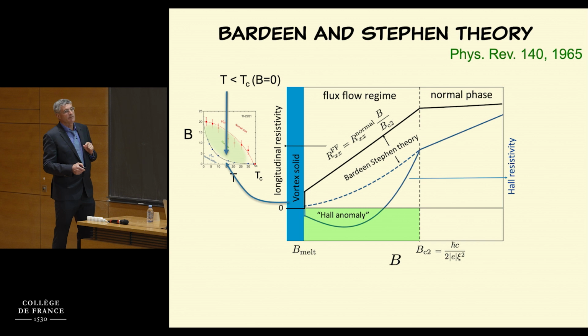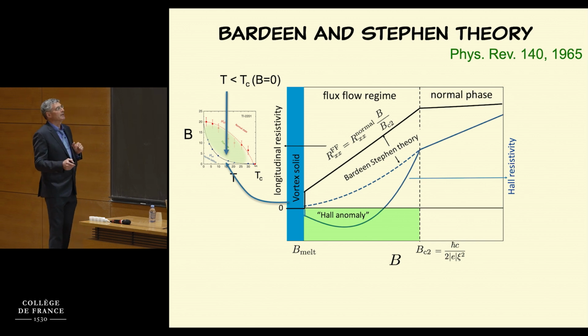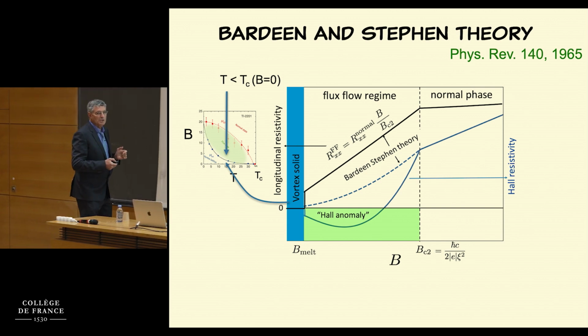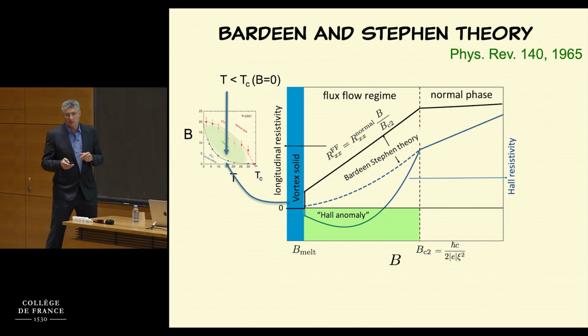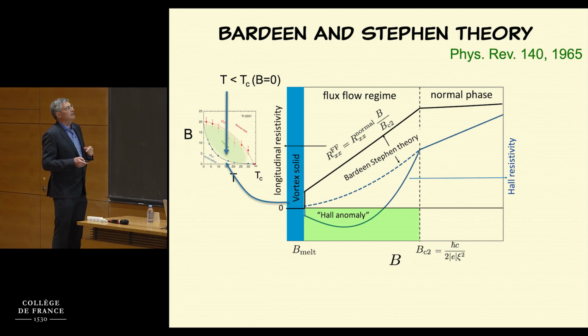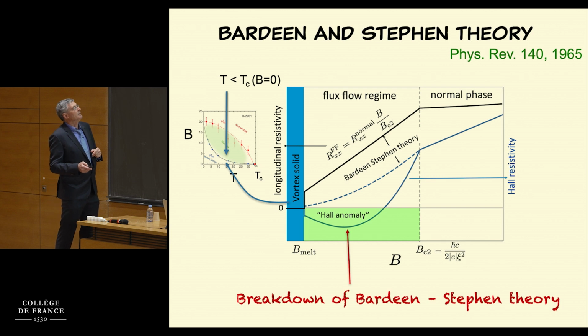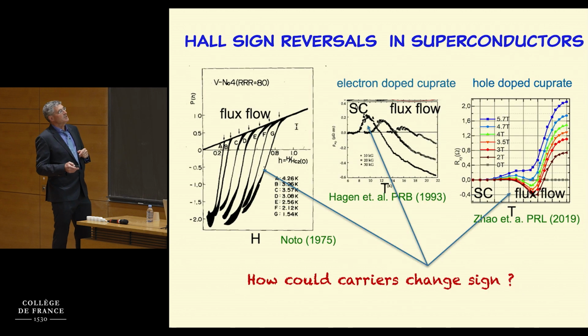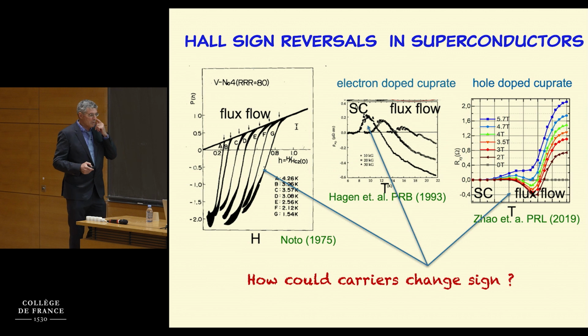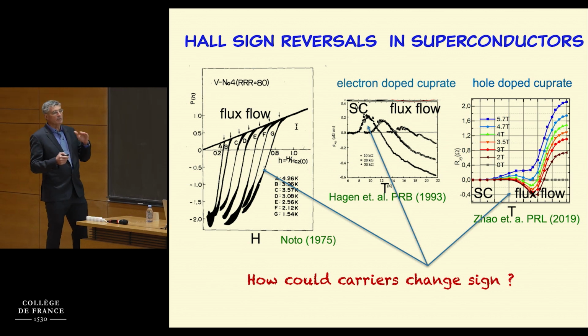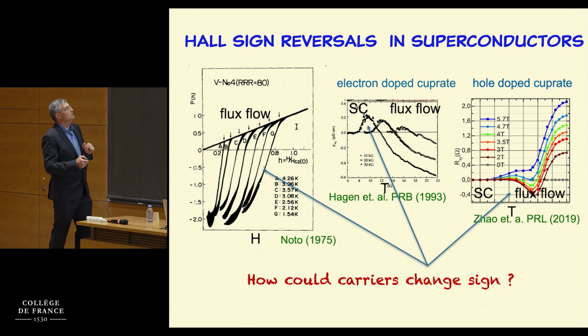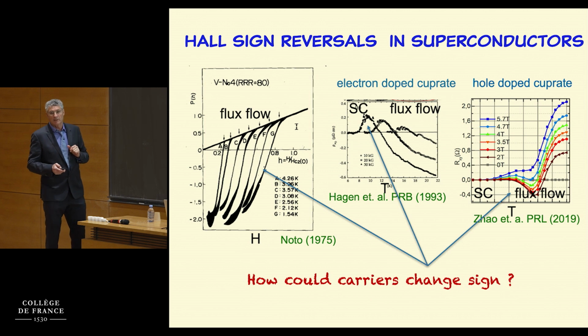Experiments that show reversal of sign are definitely in violation of that theory. So that caused a lot of confusion, lots of papers, and lots of arguments in the literature over the years until people got tired. But it was still, I think, in many minds, an open question. What would make the Hall suddenly decide to change the nature of its carriers from positive to negative? And as you can see, it happens. It happens in electron doped, in hole doped superconductors, and vanadium films, and many, many other systems. I saw it in molybdenum sulfide. Many systems have it. They have to be thin films, and sometimes disordered, sometimes less disordered. But this is an open problem and an experimental find.